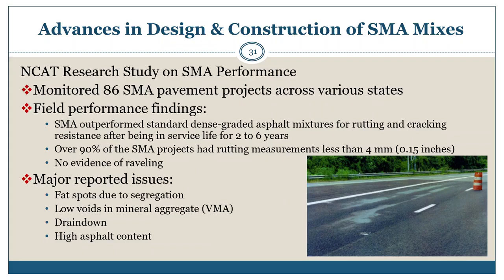In addition, there has been an NCAT research study on SMA performance. Some 86 SMA pavement projects have been monitored across various states over the short term and long term. Performance has been reported as good to excellent, with very few reported issues. So SMA mixtures in the NCAT research study have outperformed standard dense graded asphalt mixes for both rutting and cracking resistance after being in service for 2 to 6 years. Other studies have found that to be the case for over 10 years of performance.